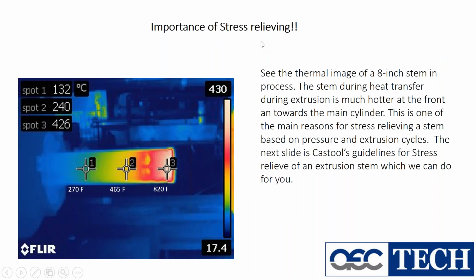Stress relieving. This is a thermal image of a stem that I took a little while ago. You can see the front end of the dummy block is 820 degrees Fahrenheit, 465 just behind the connection, 270 3/4 of the way down, and back here it's actually about 85 to 90 degrees Fahrenheit. Pressure and temperature over time will work harden the front of the stem. Most stems are manufactured at 46 to 48 Rockwell. We have seen stems come back to us for stress relieving at 60.